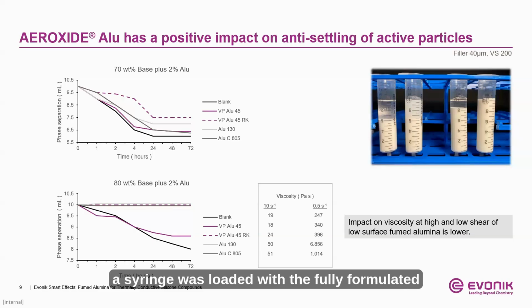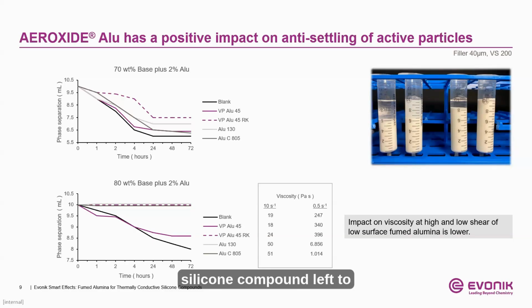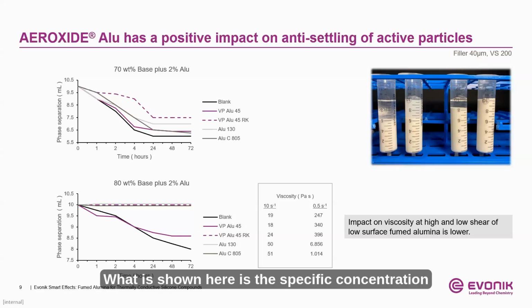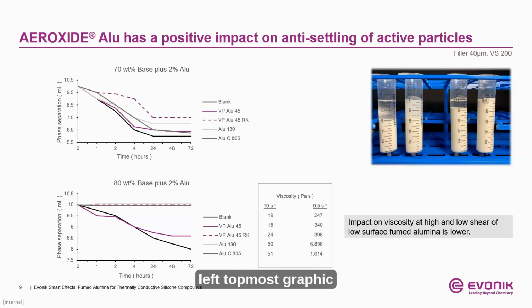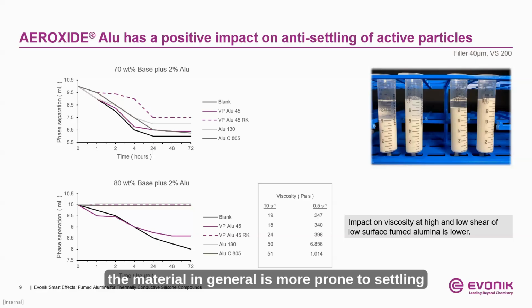Basically, a syringe was loaded with the fully formulated silicone compound, left to sit on the shelf, basically a shelf life test, and ultimately measure how many milliliters of fluid were present at the top of the syringe following any instances of syneresis. What is shown here is the specific concentration of spherical alumina plus 2% fumed alumina for anti-settling purposes. If we look at the left topmost graphic for 70% spherical alumina, and again, 2% fumed alumina added here, we see that with 70% spherical alumina, due to a lower volume fraction of solids and an overall lower viscosity, the material in general is more prone to settling and syneresis.